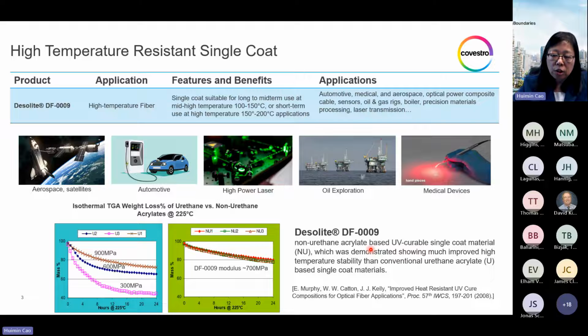These papers showed that the typical urethane acrylate chemistry used in regular optical fiber coatings suffers from severe coating degradation, due to the urethane linkage being more prone to break under high temperature. The lower the modulus, the more severe the weight loss, which is used to represent the degree of polymer degradation. In comparison, the non-urethane-based chemistry is much more stable and not that sensitive to different levels of modulus. DF-0009 was designed at around 700 megapascal, which is a medium-high level, appropriate as a single coat.